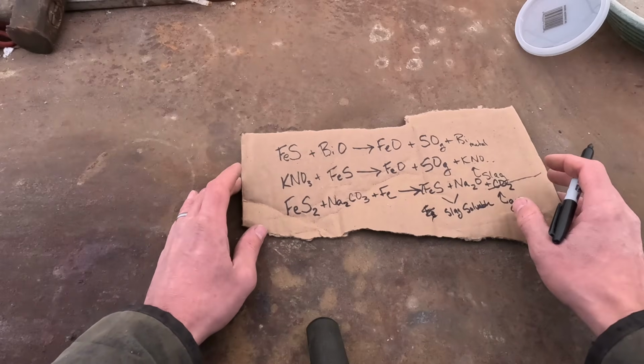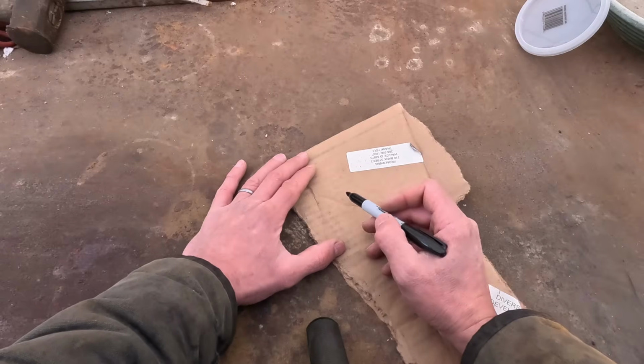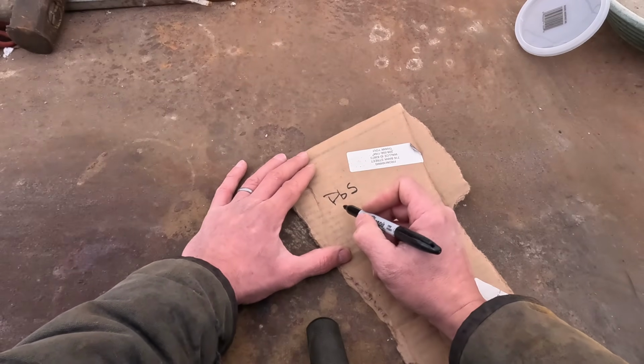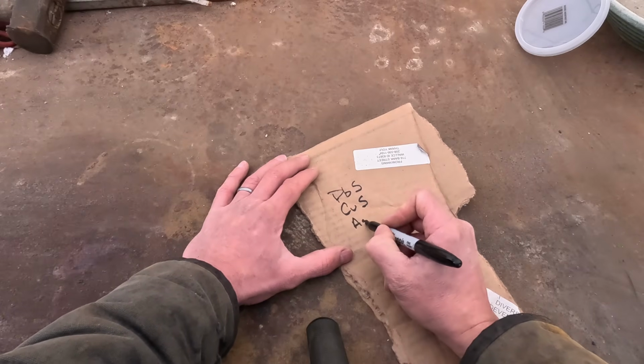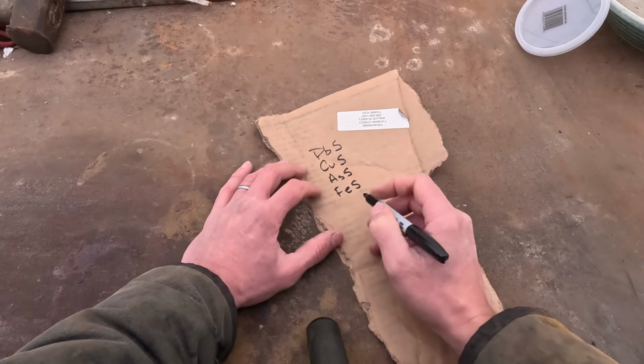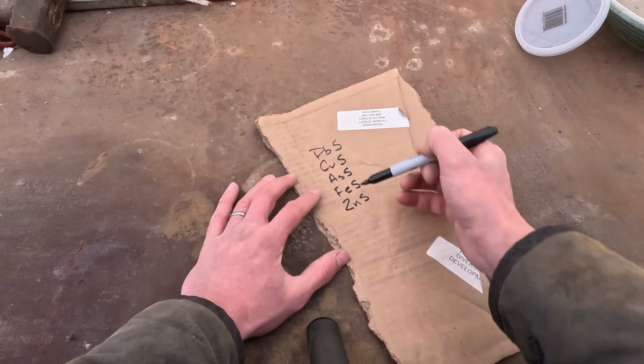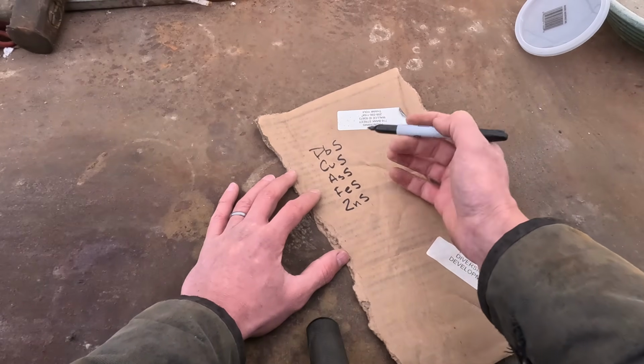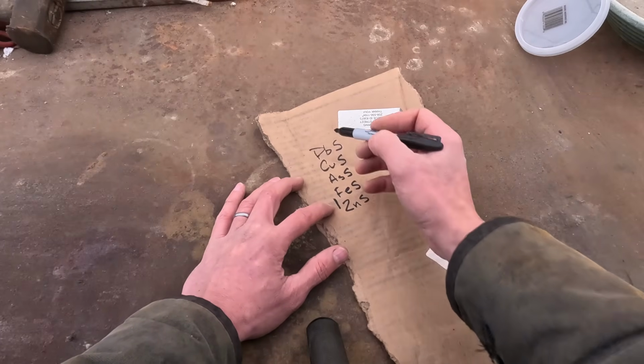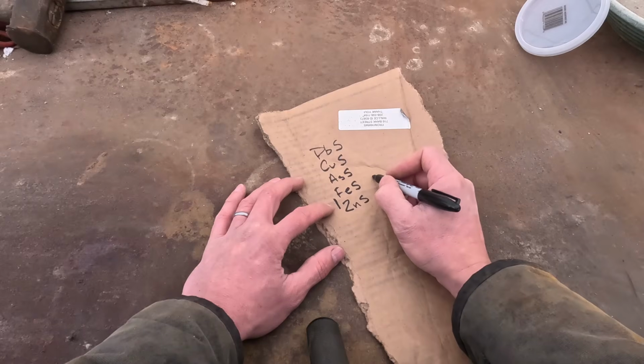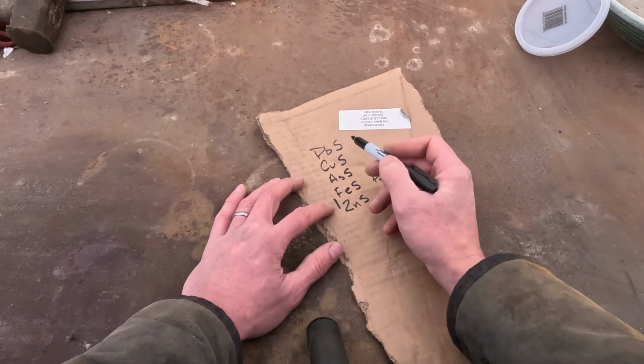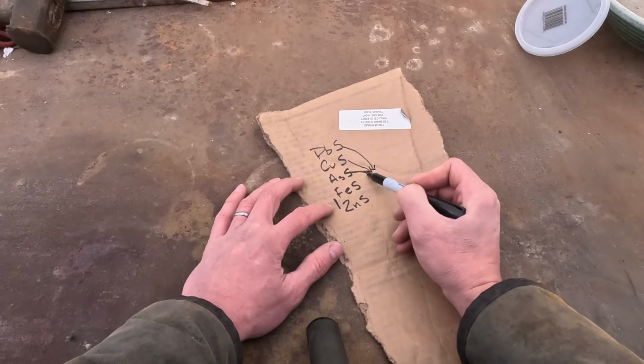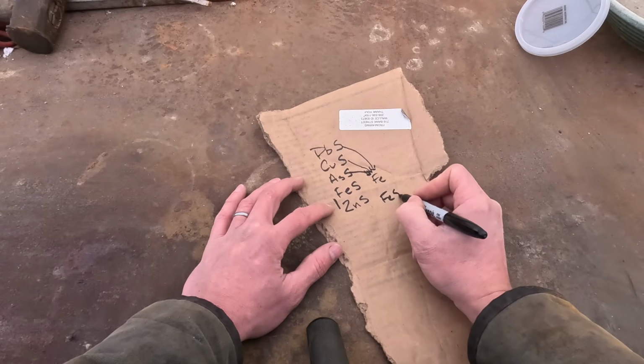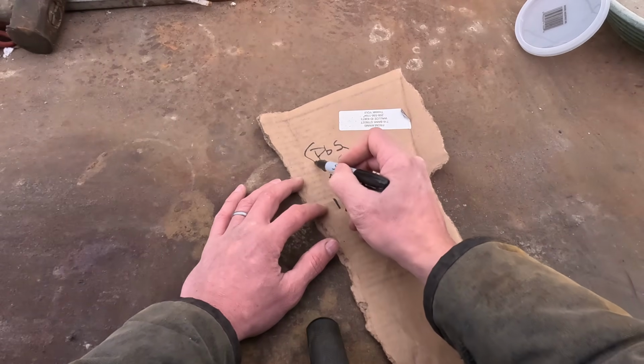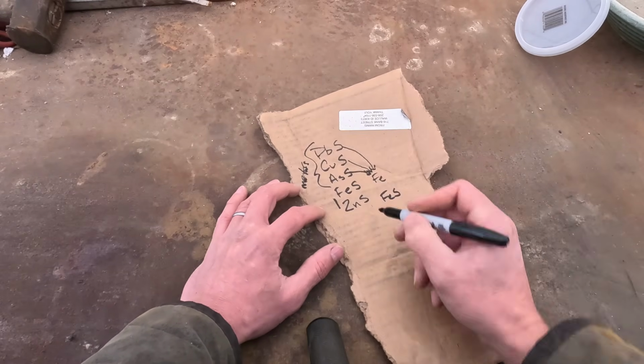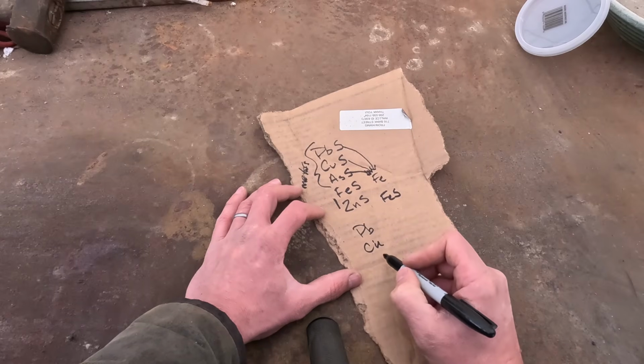There's another component to this, which we have to talk about actually, and this is getting way too complicated, and I don't know if anybody cares about this, but we're gonna flip this over and talk about this. So, iron sulfide is a very common sulfide, but there's also lead sulfide, there's copper sulfide, there's arsenic sulfide, zinc sulfide. And to understand this, we have to talk about the metals reactivity chart. Iron and zinc down here are very reactive. Lead and copper are not. And so if you have an iron metal, it will rob the sulfur from these less reactive metals. You will end up with iron sulfide, which we can make soluble in our slag, and metals.